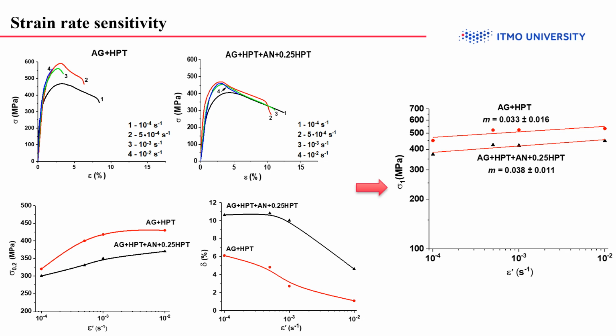It is known from the literature that the upper limit of the time required for the formation of dislocation pileups in grain boundaries at room temperature in HPT processed aluminum is about 6 seconds. Such time is already comparable with the time needed to reach the yield stress at a strain rate of 10 to the power of -2 reciprocal second. In this case, grain boundary dislocations simply do not have enough time to form sufficiently powerful pileups in grain boundaries, which leads to lower plasticity and even suppression of the plasticization effect at higher strain rates.